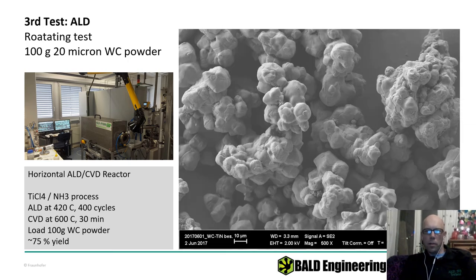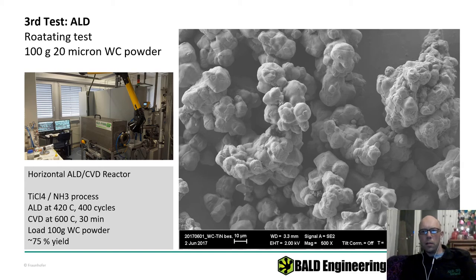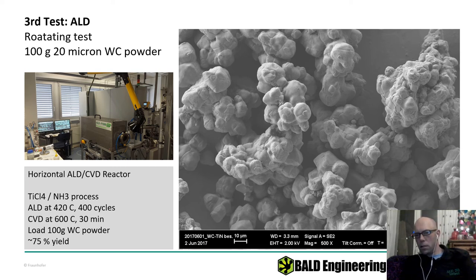Here's the powder — polycrystalline fine-grained tungsten carbide, super hard stuff. This has been coated with titanium nitride by ALD using a 20 nanometer recipe, 400 cycles at 420°C, with a growth rate of 0.333 Å per cycle plus some incubation cycles.